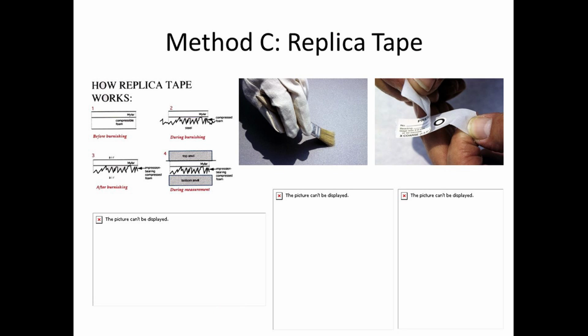Once we create that impression, we remove the tape from the surface and we have a choice. We can put it in a spring-loaded micrometer that gives us the reading in mils, or we can insert that tape in what's called a replica tape reader that will read the depth of the surface profile, store that information, which can then be uploaded to software or downloaded to a printer, whichever is preferred.